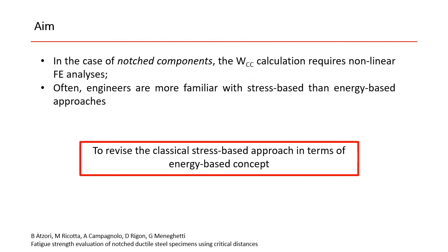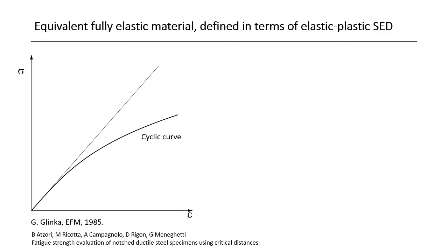In the case of notched components, the evaluation of the elastic plastic strain energy density requires nonlinear finite element analysis. Moreover, often engineers are more familiar with stress-based than energy-based approaches. Therefore, the aim of this work is to revise the classical stress-based approach in terms of energy-based concepts. In view of this, an equivalent fully elastic material was defined, which assures that the elastic plastic strain energy density evaluated at the fatigue knee is maintained.